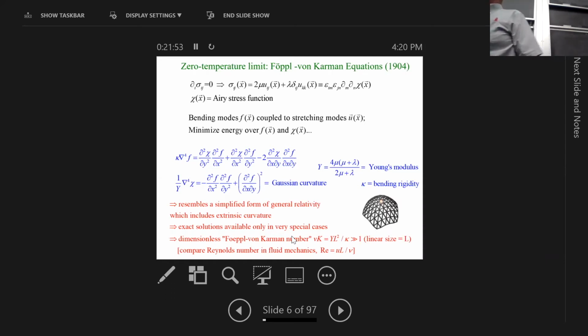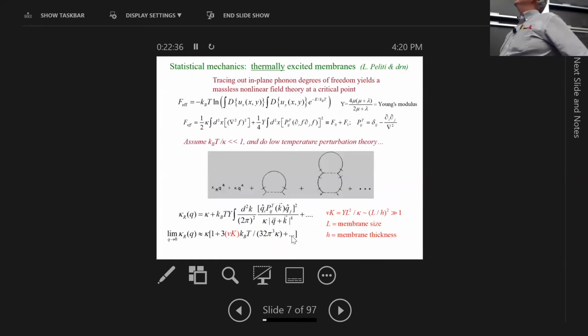That's what happens in the Navier-Stokes equations, the limit of vanishing viscosity. And the analogous thing to a Reynolds number, here's the Reynolds number for those of you who know what it is, for a viscous fluid with viscosity nu and speed u and size L. Here's the quantity that you can scale out and show controls everything. It's this Foeppl-von Karman number. And if you put in Young's moduli for paper and bending rigidities, and you have an 8.5 by 11 piece of paper, this Foeppl-von Karman number, which measures the strength of these nonlinearities, is 1 million. For graphene, it's 10 to the 12. So that already makes graphene kind of interesting, in my view.